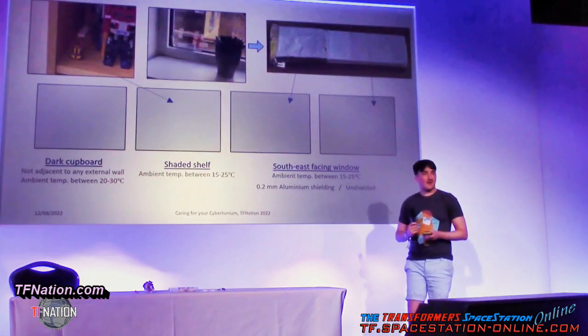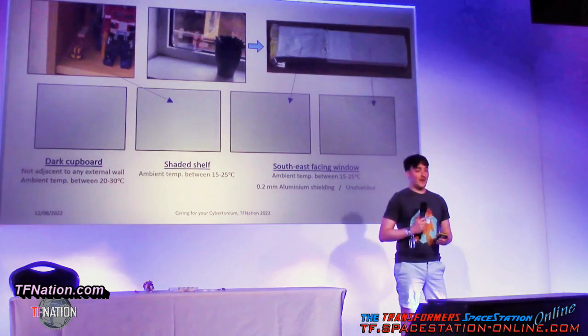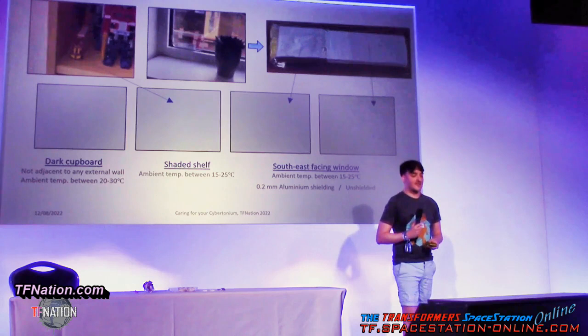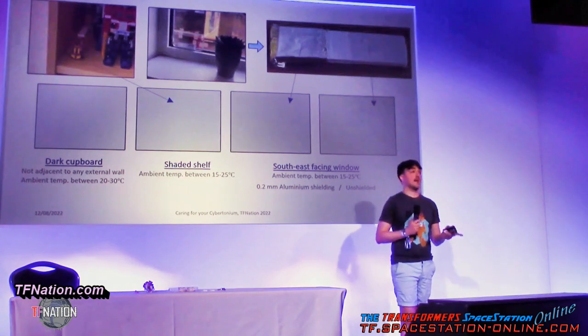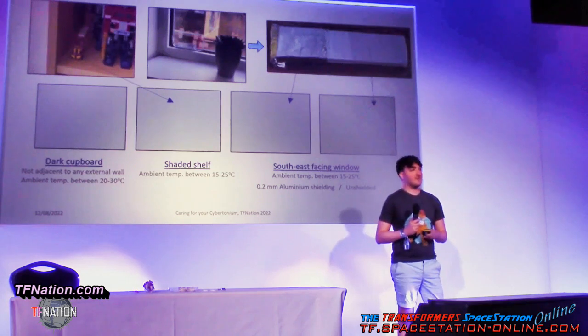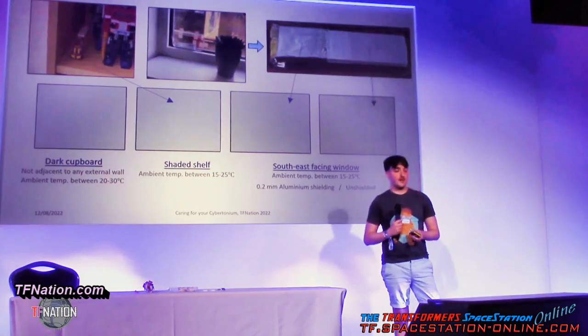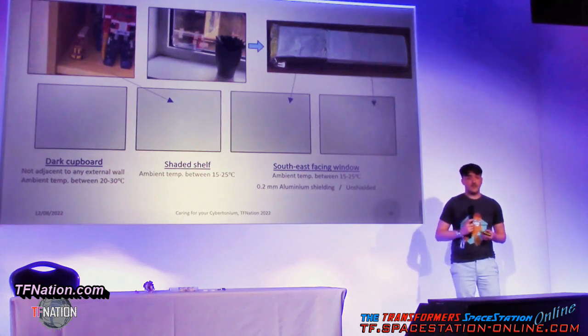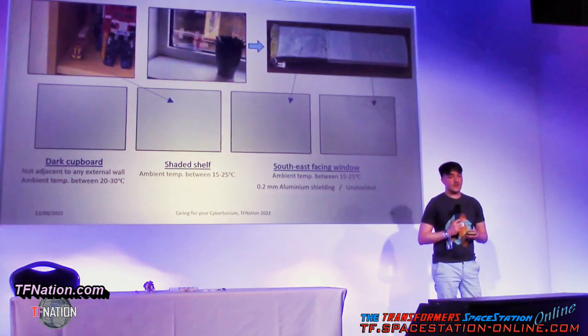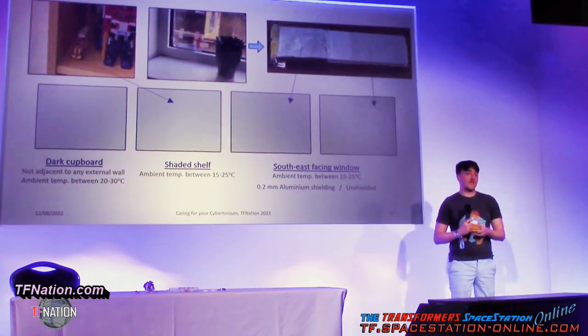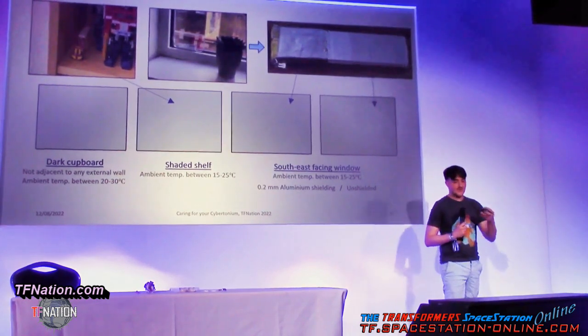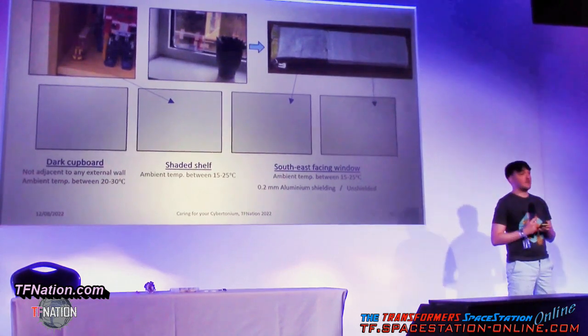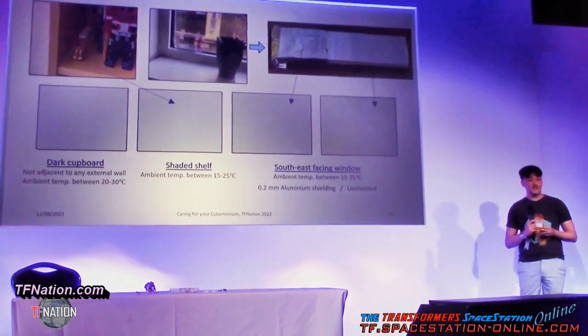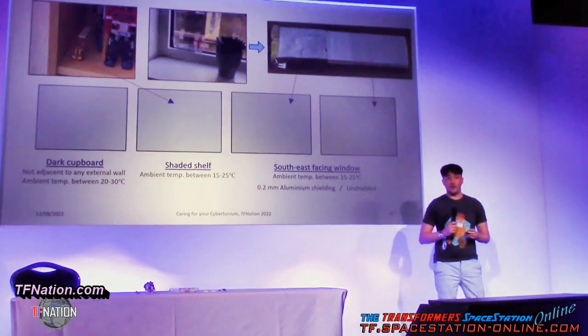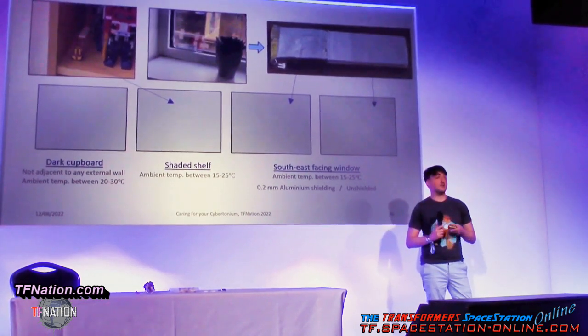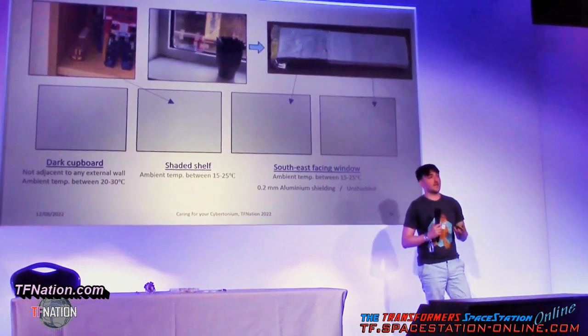So, our lateral flow test. I had one, which was a control sample, which was on a dark shelf. Well, no, two. I had one in a dark cupboard. The second one on a shelf, which is in a light room, but not in direct sunlight, which is the top left picture. And then the experimental one, which was on the windowsill. And then importantly, half of it I covered up with aluminium foil. I wrapped it several times. It had an effective aluminium shielding of 0.2 millimeters, 200 microns. Whereas the other side was untouched. And in the middle, I painted it using just some Warhammer acrylic white paint.